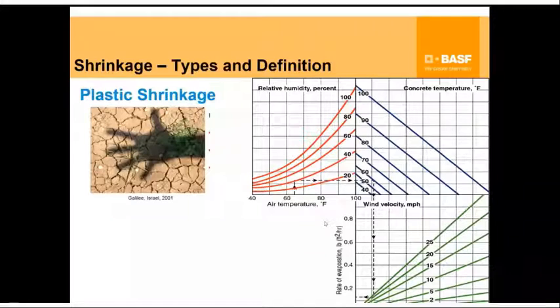There are three primary factors that affect it. The relative humidity: if you have a high humidity environment, obviously the evaporation rate is decreased. If your concrete temperature is very high, the evaporation rate is increased. And if it's combined with wind velocity, if you're constructing in a wind tunnel area, then this effect is seriously exaggerated. And this nomograph is available, and Piyush will talk about it in his presentation as well, as to how this nomograph can be used to understand the rate of evaporation and therefore the propensity of plastic shrinkage.